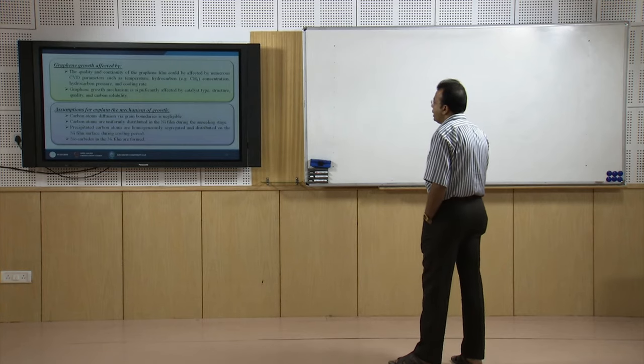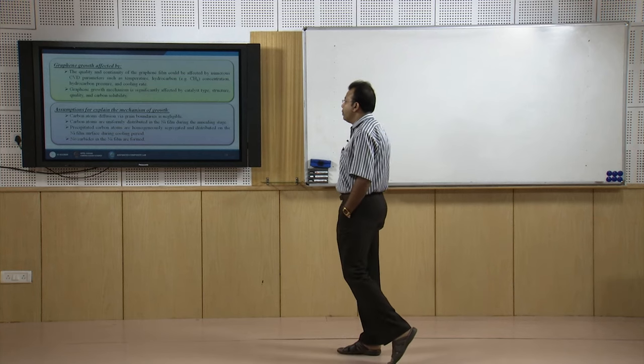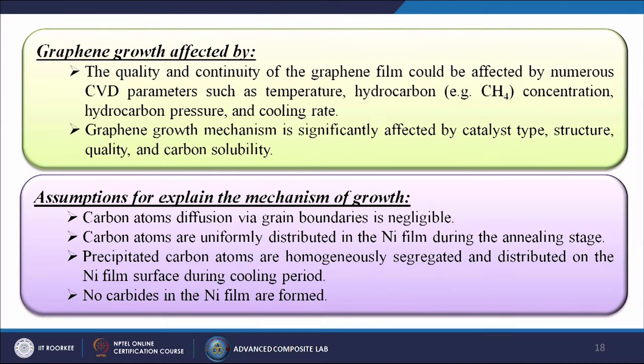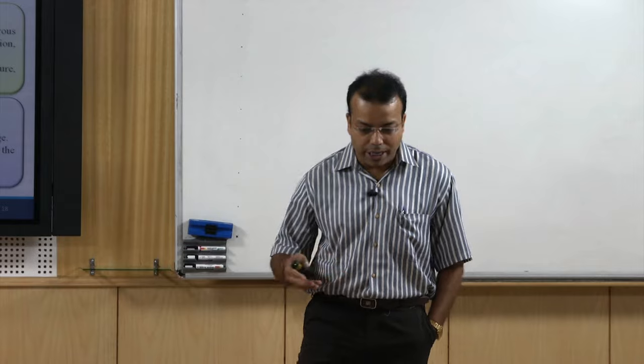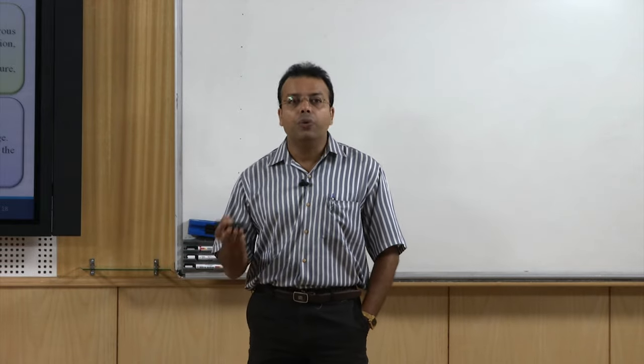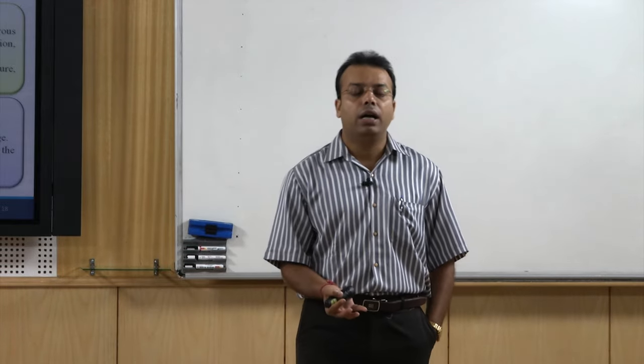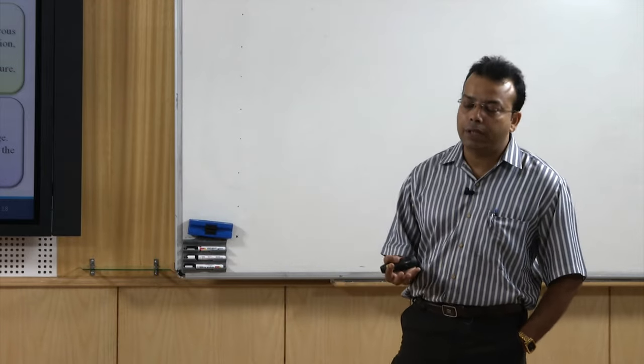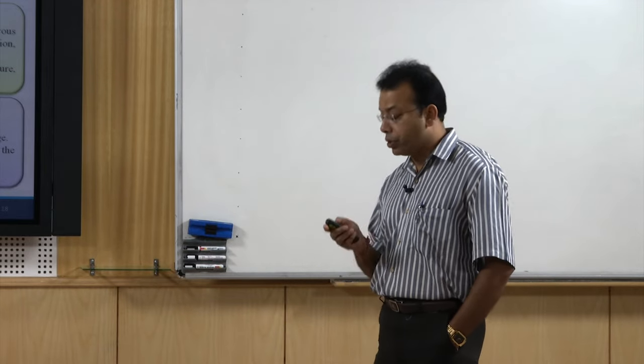The graphene growth rate, and the quality and continuity of the graphene film, could be affected by numerous CVD parameters such as temperature, hydrocarbon, that is methane, concentrations, hydrocarbon pressures and the cooling rate. The graphene growth mechanism is significantly affected by catalyst type, structure quality and carbon solubility. So these are all important input parameters by which we can control the growth rate of the graphene onto the nickel substrate.